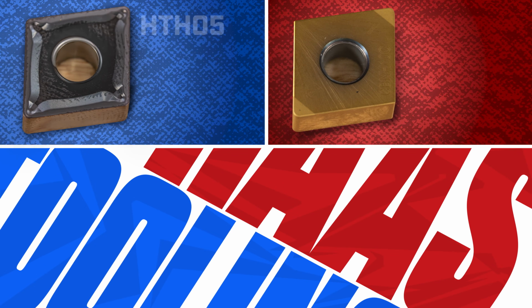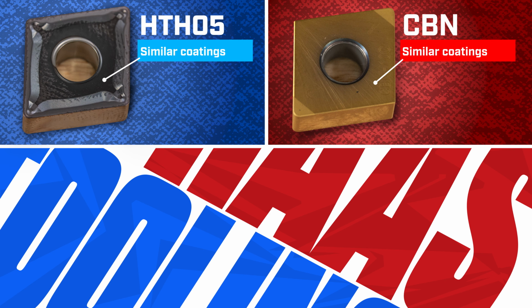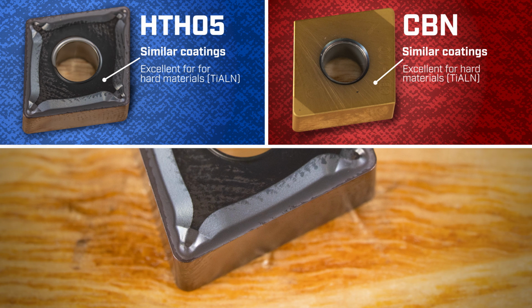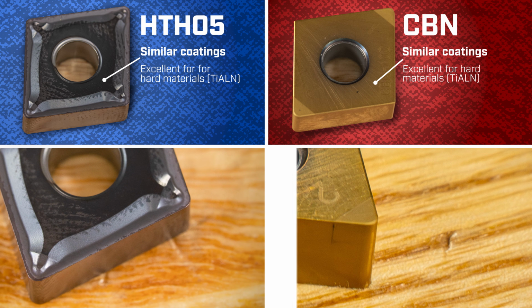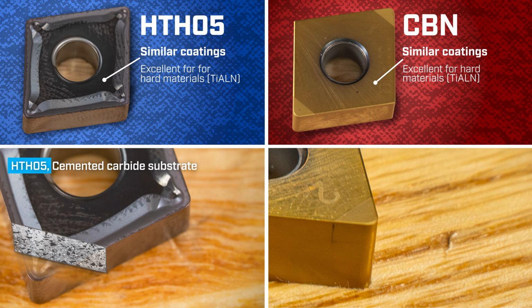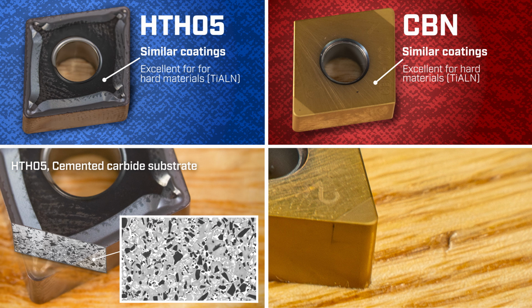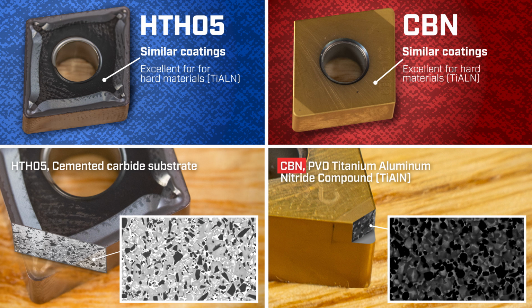Let's look at both the HTH05 and the CBN and examine which one will work for you and your applications. The coating is similar on both. It's a PVD titanium aluminum nitride compound, but it's what's underneath the coating where they differ. The HTH05 insert is a cemented carbide substrate, and the CBN inserts have a brazed tip compound created by sintering a mixture of cubic boron nitride, CBN, and a ceramic binder, forming a substance that's nearly as hard as diamond.